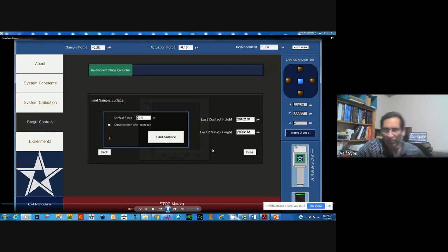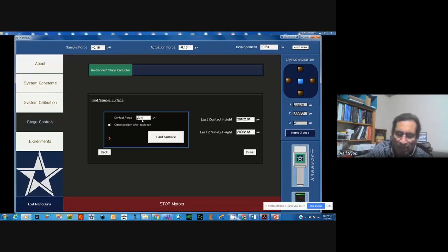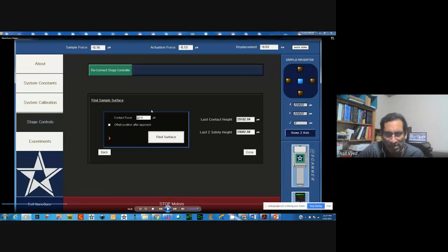And now in this window, you can see that there are certain parameters that need to be put. The important parameter is the contact force. Basically, as the tip makes contact with the sample surface, it has to maintain a certain amount of force. That is the force that we are going to give here as contact force. So when it makes contact and feels that 2 micronewton force, it will stop. Okay. So for example, when you put the number there and then you run, it's a 2 micronewton force,